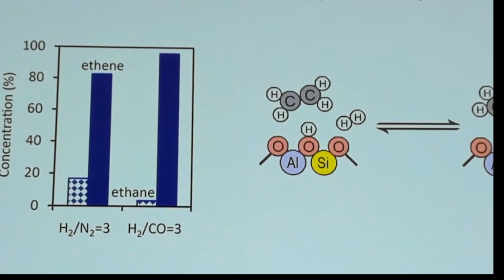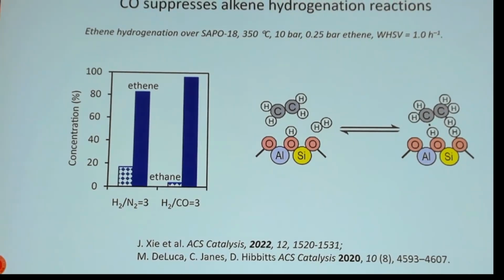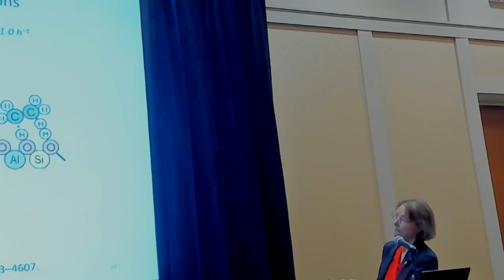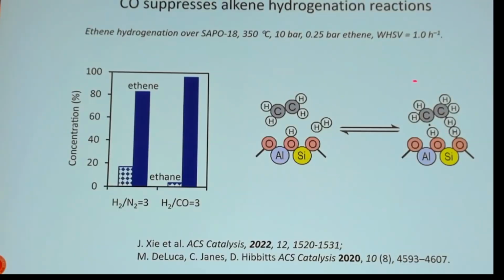Now, we know from theory work done in the Hibbitts group that the hydrogenation of olefins and other components happens by heterolytic splitting of a hydrogen molecule over a Brønsted acid site and its neighbors. This is also what we think is happening here. So the role of CO in this context, we don't know, but of course we can speculate that CO will adsorb on one of these oxygens and therefore outcompete the hydrogen sorption and reaction.